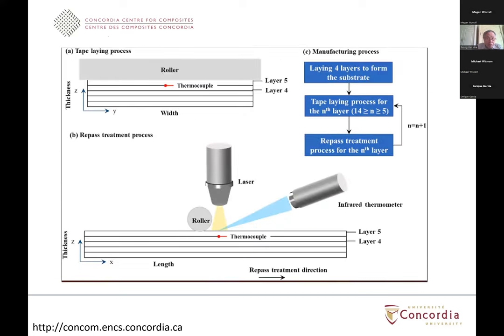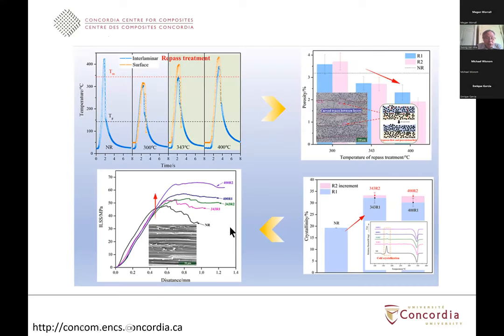So they showed the result in the sense that what happens here, you have a few layers and they do the repass over the layer. And this is the result. These are the temperatures at the interface. In one case, it's more than the melting point. Another case, lower than the melting point and so on. And they show that in terms of varying the temperature at the interface, you compare between this case here for interlaminar shear strength.